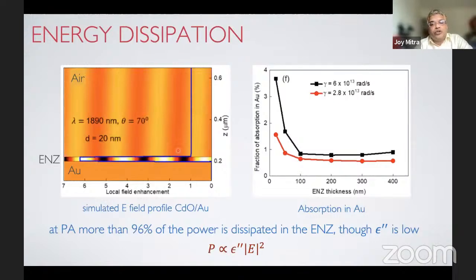And ultimately, to show that indeed the ENZ film is doing the trick of perfect absorption: where does the energy go? There is zero reflectivity. The energy is completely eaten up by the structure. We show here a calculation of air, ENZ, gold. Okay, and this is done at around 1890 nanometers. So gold is highly reflecting, and you have a thin film of ENZ, which is just 20 nanometers in thickness.